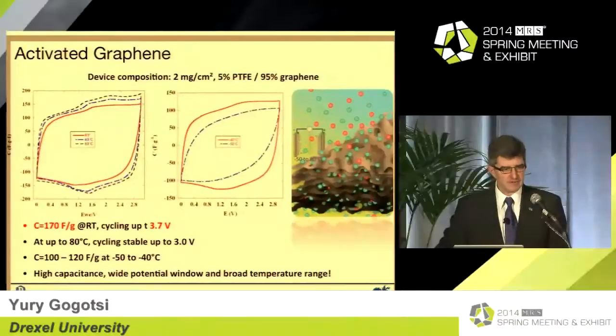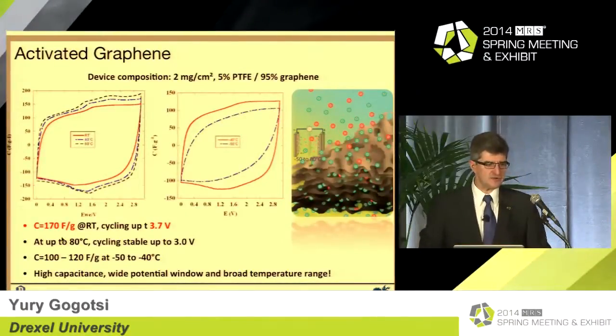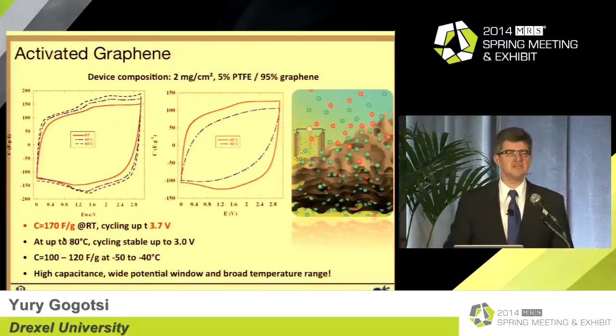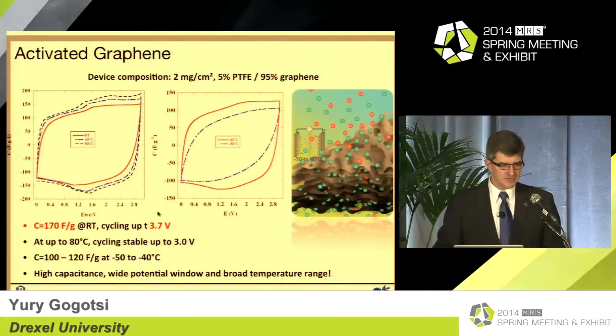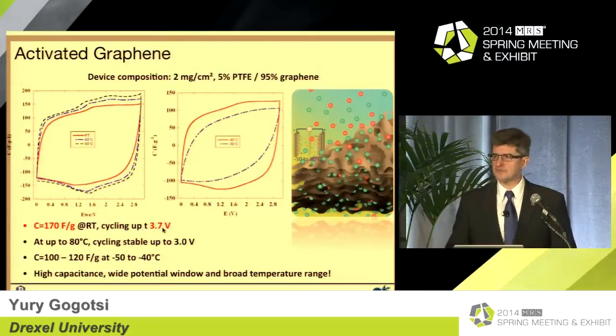So what we did, working with Rod and his group, we produced supercapacitors using the same ionic liquid eutectic mix that I showed you before in application to carbon onions and nanotubes. But now what we obtained by using graphene, where again ions don't have to diffuse through a network of pores but jump into holes in layers of graphene, we were able to achieve about 170 farad per gram capacitance, which is at the level of the best organic electrolyte supercapacitors. But we were able to go up to 3.7 volt.